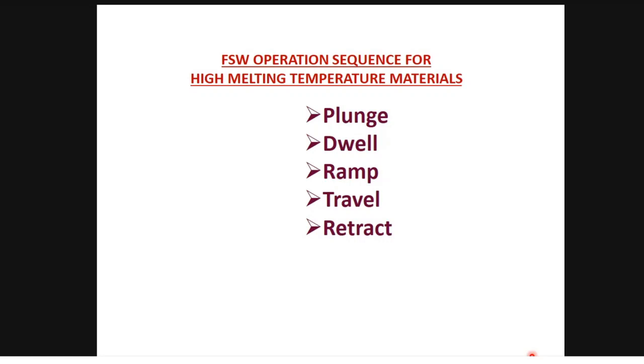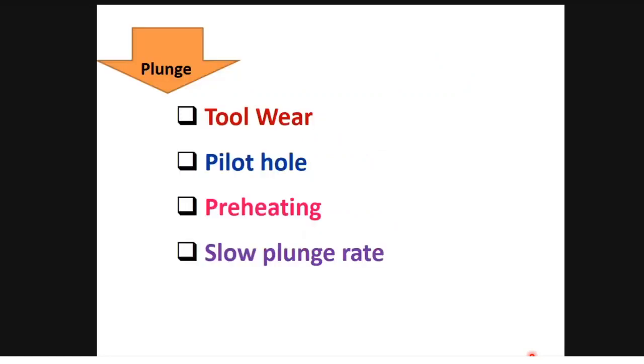After plunging, you have to give sufficient time for preheating. That time is called the dwell time. From the dwell time, you should not increase the welding speed rapidly. You have to increase the speed very gradually. That is called the ramp stage. So in high melting temperature materials, all the stages are essential: plunging stage, dwell stage, ramp stage and travel stage, because a lot of forces are acting.